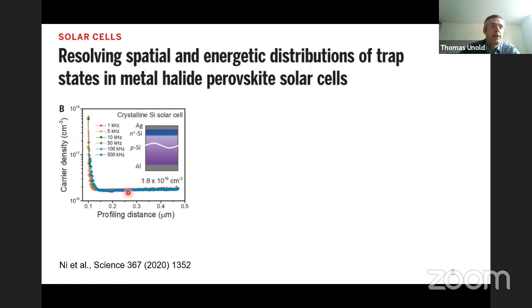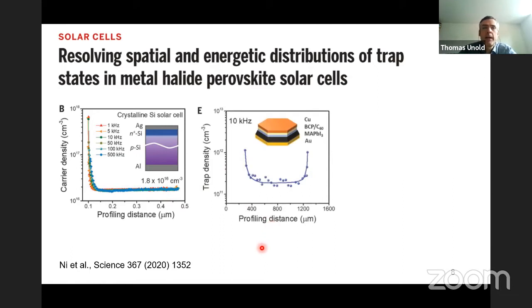So it's a crystalline silicon solar cell, and here they show the carrier density over profiling distance. It's what I just showed you on the last plot. That's about 2 × 10^16, which is actually the density they have in their wafer. Okay, and then they move on to the perovskite, and they made a very thick crystal. So they do the same measurement. You see here the profiling distance is a millimeter. So it's actually a millimeter thick crystal, and they plot the trap density, and it's about 2 × 10^11 here. I think this is also a very nice measurement, and no issues with that.